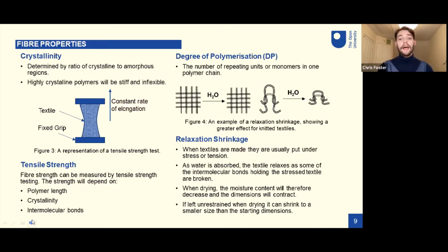When textiles are made through the process, if they're woven or knitted, they're usually put under some kind of stress or tension. And when this occurs, the textile can then remain in that stressed position through forming intermolecular bonds in that position. When water is absorbed, the textile can actually relax as the intermolecular bonds holding the textile in place are broken. And this effect can then lead to shrinkage, because once the textile dries and the moisture content decreases, if the textile remains unrestrained whilst drying, it can actually shrink to smaller sizes than the starting dimensions. And this effect is usually seen more for knitted textiles than woven textiles.